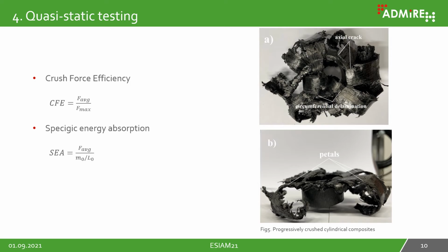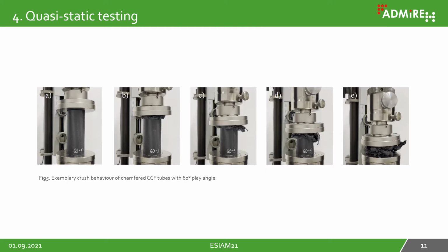On the right side in figure 5, you can see progressively crushed cylindrical composites. In figure A, you can see the axial cracks initiated by the quasi-static compression testing and the circumferential delamination. In figure B, you can also see the petals which are formed by compressing the tube. The quasi-static compression tests were performed on each set of specimens.